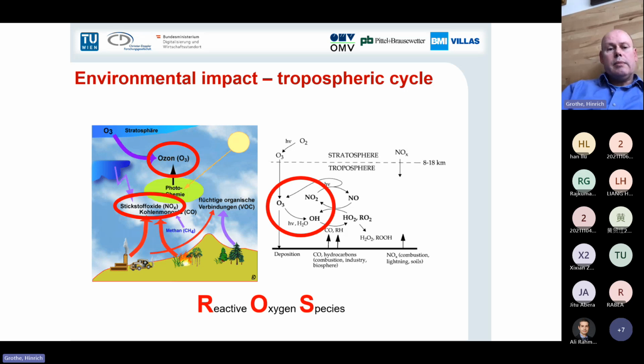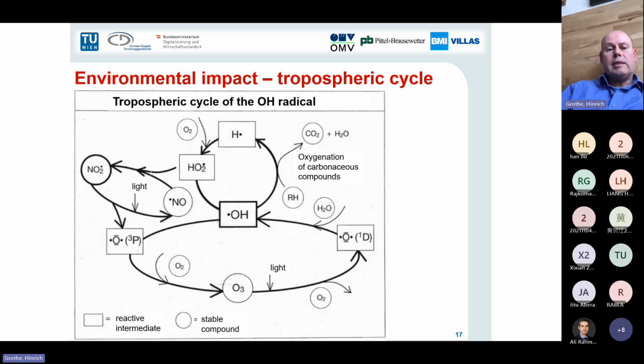So let's talk a little bit about the troposphere and these reactive oxygen species. The main components are ozone, nitrogen oxide and OH radicals. And they are formed in the so-called photosmog, which happens during daylight. And here is such a tropospheric cycle for the OH radical, and I will try to explain that a little bit to you. The whole story starts with the NO2. The NO2 is a radical, and the NO2 is emitted, for example, from combustion engines, but there are also known natural processes which produce NO2.